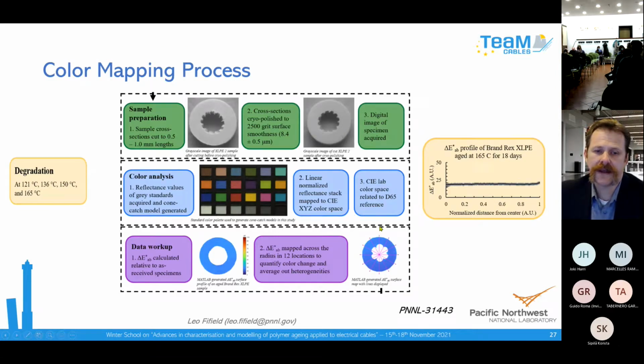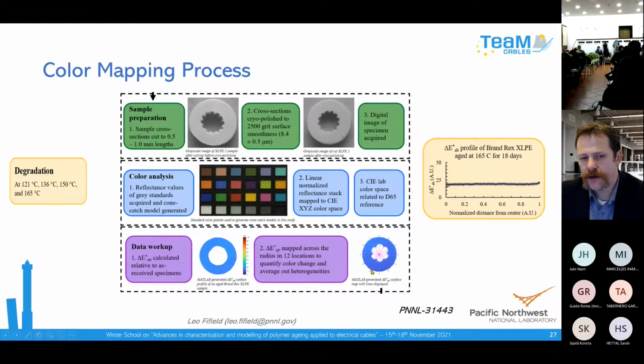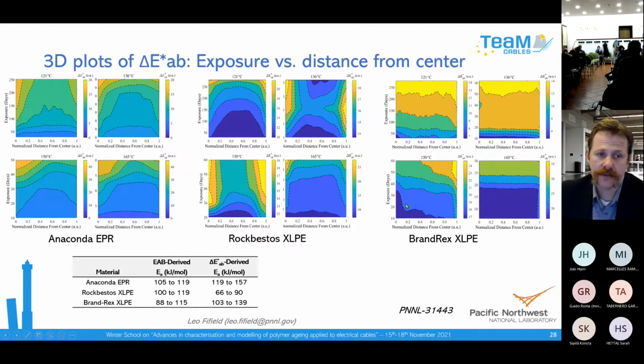Here is the new technique we developed using color change on these similar samples. As cross sections are polished, we're able to image the whole slice of the cable insulation all at once, and then quantify the color change locally with just optical microscope resolution. And then we can track, normalized through the thickness of that insulation, the behavior across the thickness. So that's how we pursued it.